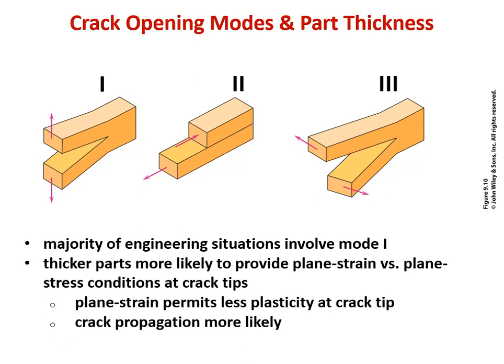The one that is most likely to make that crack propagate for a given unit of stress, like say we apply 10 pascals in each of those three different directions, that 10 pascals is far more likely to propagate that crack if it's loaded in the alligator mouth, mode one. That is the most severe loading mode, stress per stress, material for material, and pre-existing crack length for pre-existing crack length. So quite often when you read about fracture toughness test data, you will hear about mode 1 loading.